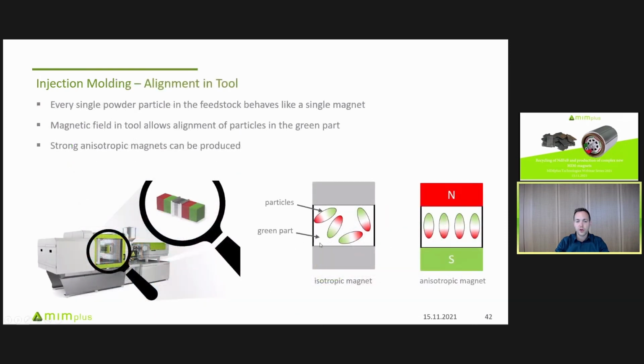If you take a closer look at a tool and at the feedstock, you can imagine that every single powder particle shown here behaves like a single magnet. And if you put a magnetic field onto that feedstock, you get an alignment of the particles, and the particles are pre-aligned in the feedstock. The feedstock solidifies, and the pre-alignment is stable in the produced green part. And then you can produce so-called anisotropic magnets. This pre-alignment stays stable until you reach the sintered magnet in the end.